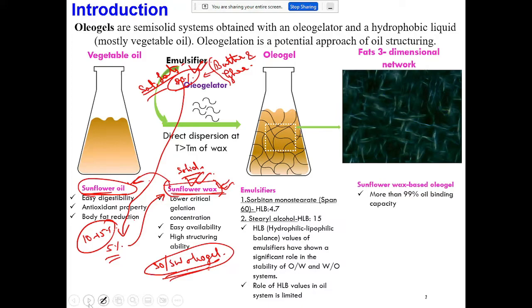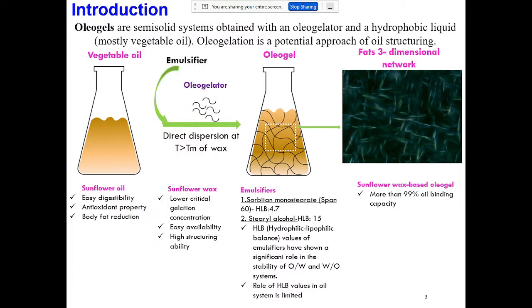As you see, what are the advantages of the sunflower oil? The advantages are easy digestibility. It has antioxidant property, which would give increased stability during the shelf life, and it also helps in body fat reduction. What are the advantages of the sunflower wax? It has a lower critical gelation concentration. That means it can gellify the vegetable oils at very low concentrations, and in our case we found out that for the sunflower oil it was 5%.